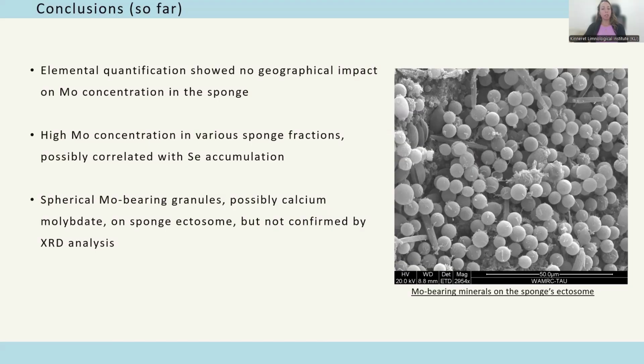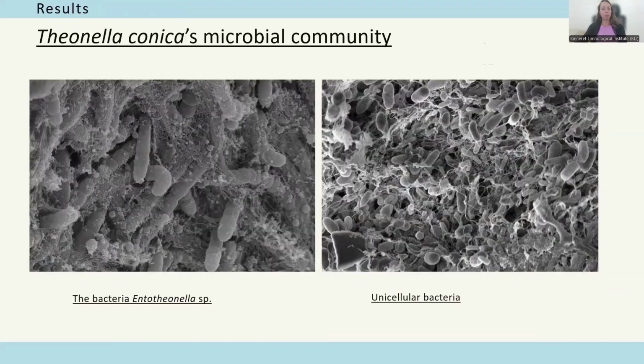Together, these results suggest that molybdenum accumulation is actually organized inside the sponge, and that both the outer sponge region and microbial symbionts may be involved. This brings us to the microbial community, and especially to Entotheonella, seen here on the left image. When we examined the sponge ectosome by SEM, we saw a dense microbial community. This includes many unicellular bacteria, seen here on the right, and a high abundance of filamentous bacteria identified morphologically as Entotheonella and later also genetically.